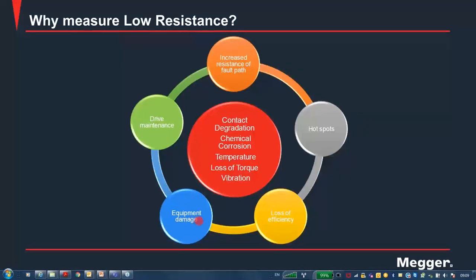And for the extreme cases where there is high enough resistance, the failure is going to lead to cycle heating, and that heating may damage the contact or any surrounding insulation, which is basically not a favorable situation. And with low resistance measurement, you can trend it over time, and if you see an unacceptable increase in resistance, you can have your maintenance group come and perform work, so you can draft your maintenance strategy to be predictive, and you have more control over this situation. So this is actually the reason why we measure low resistance.